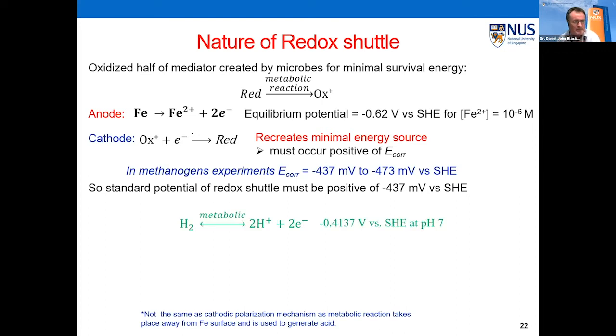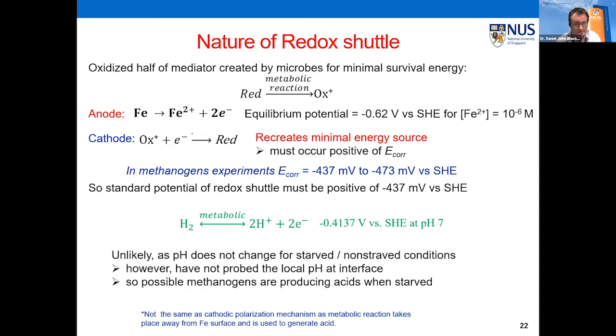Okay, just about could be hydrogen, which actually with the species would be proton. So it could be that you take hydrogen in the bacteria and produce protons, and then the proton is being reduced. That's not quite the same as the cathodic polarization mechanism because the hydrogen processes occurring away from the electrode surface. Okay.